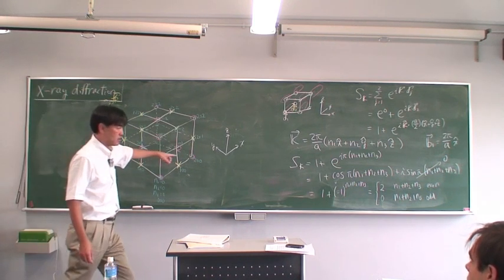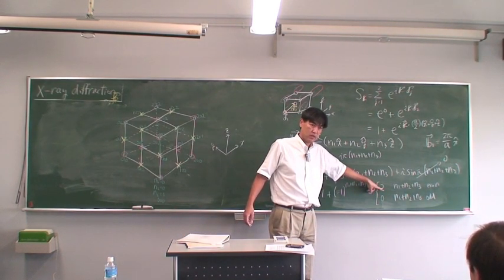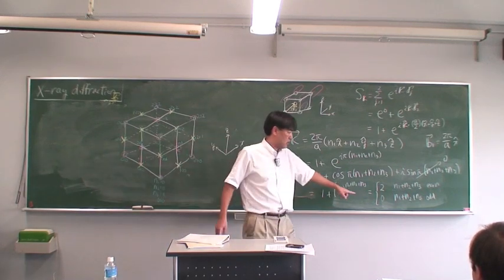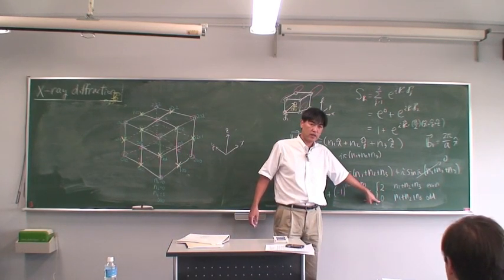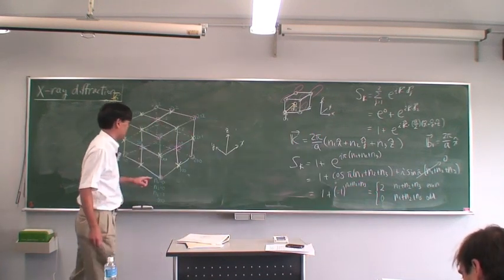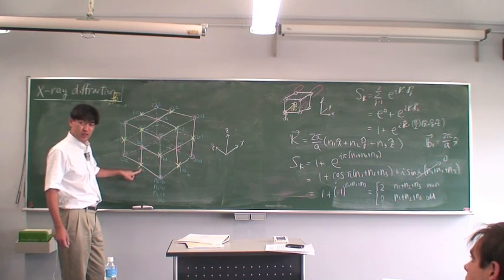And I said, this has a strong amplitude, right? That's what the structure factor does. And this amplitude is 0. So practically, the intensity is 0. So all I'm saying is that those yellow points disappear. Yellow reciprocal points disappear.